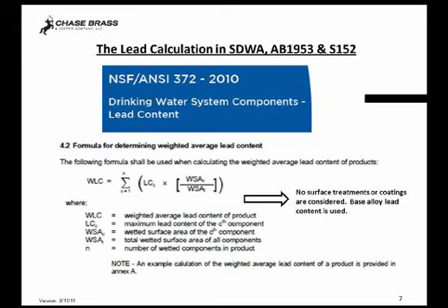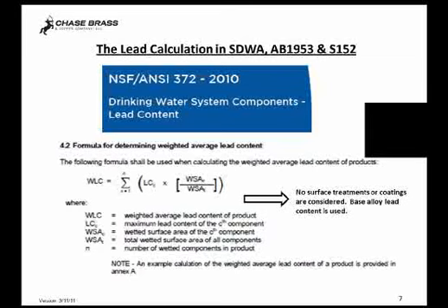And Larry, I think that's an important comment to make, a distinction of. Previous to the California and Vermont legislation, which ultimately drove this national legislation, most of the requirements related to our customers' products were leachate and therefore performance-driven. So they could get away with coatings or washes typically to still be compliant. This evolution of this legislation really is saying they are very focused on the content of the metal, more a prescriptive-based legislation as opposed to a performance-based legislation. So this has been a substantial impact and deviation from what our customers have previously had to deal with compared to today.